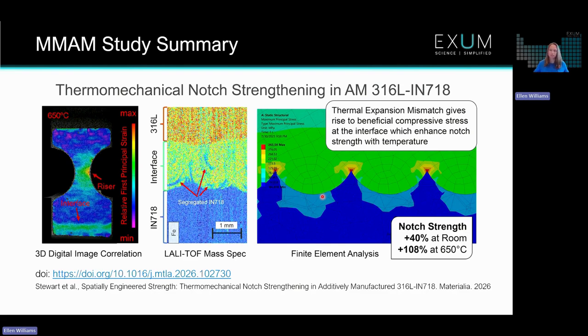And this finite element analysis is really critical in explaining why. So, overall, great work by the researchers creating these strengthened tensile bars, demonstrating that multi-material additive manufacturing can create parts with significant strength compared to parts with just a single alloy. But what these different characterization tools showed across the interface is that there is room for improvement. There's room to further optimize printing parameters and what happens at that interface so that we aren't seeing as much of that segregation. Maybe we aren't seeing some of those lathe structures that we identified with the SEM-EDS. So that was certainly one of the key takeaways.